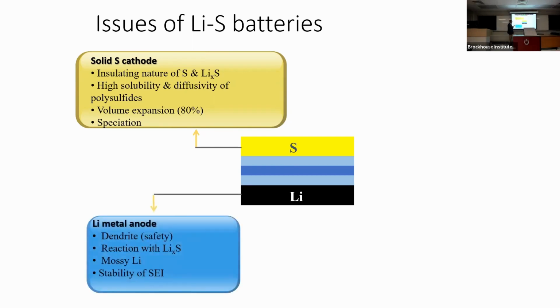And here, a lot of energy comes from the fact that you're going to use a pure lithium metal anode. The anode factor is going to be 1, not 0.1. The reason why we can do that is although the dendrite will still form at very high power rate, you cannot stop that because you are forcing the growth rate because the electrochemical gradient is very high. But we also know because of this diffusion and the reaction between the polysulfide, it's a polishing action. If a polysulfide diffuses to the lithium side, then it starts polishing the dendrites. So at least at the low power rate, it's a very safe battery that can use pure lithium.